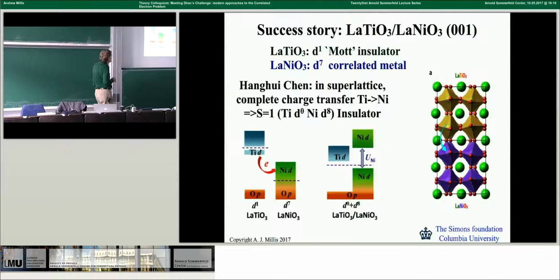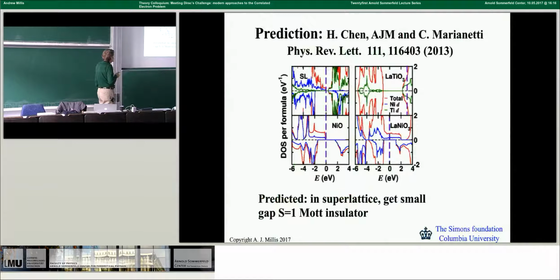All right? So this is the cartoon. Basically, you transfer charge from this material to that material. Transferring the charge changes the electronic structure here, opening up a Mott gap. Right. So that was the idea. We did a variety of calculations which are shown in this unfortunately complicated picture.